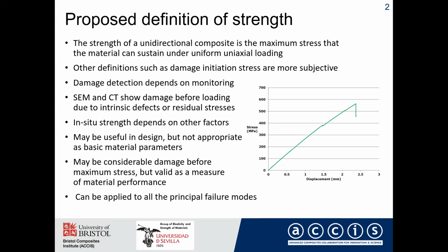If you look more closely, you might see that. If you look with a SEM or CT scanning in situ, you'll see it failing even earlier. And in fact, there are quite likely going to be damage due to intrinsic defects or residual stresses even before you actually put any load on it if you watch it closely enough. In situ strength is another concept, and that depends on many factors. And again, Federico will touch on this in a minute.